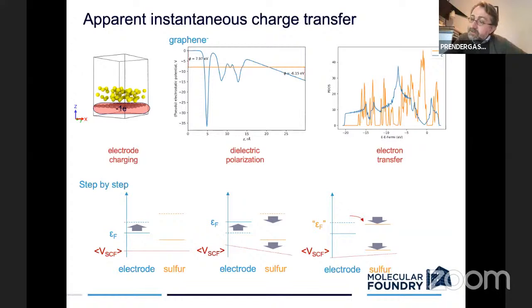I mean, I don't think this principle would be removed if I did constant potential. The only thing that would be different is that I would have a specific equilibrium charge state for the surface that would be consistent with a given potential. If there were observed potential fluctuations, actually, I'd be even more concerned, because let's say an ion arrives from solution and becomes unscreened by the solvent.